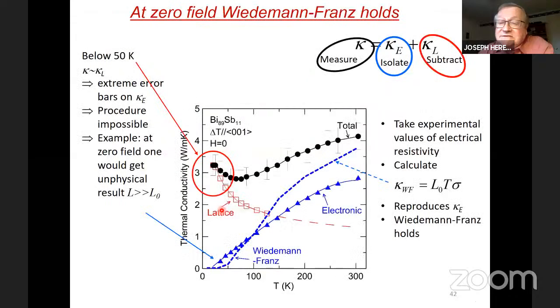Okay, so we already showed the separation at zero field, kappa into kappa lattice and kappa electronic. If I take this kappa electronic and I take the resistivity at zero field for the same sample, I can calculate, putting here the free electron value, what the Wiedemann-Franz law should be. And that is the dashed line in this plot. By my book, this dashed line reproduces the data quite well.